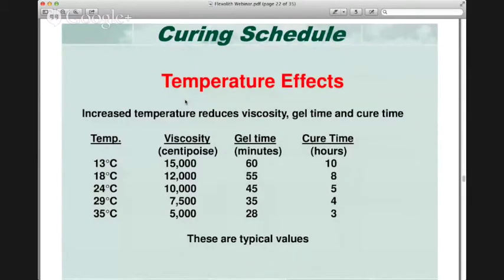Now, the curing schedule quite often dictates the type of resin that we use for this sort of product. This temperature chart here is just to give you an indication that when we install this type of product at typical summer temperatures at, say, 23, 24 degrees Celsius in the middle of the chart, the viscosity of this product is in the range of about 10,000 centipoise. So it's a fairly viscous material. Goes down, I would say, thinner than honey, for sure. But this gives us a gel time where it starts to react of about 45 minutes, so adequate working time, with a cure time of about 5 hours.